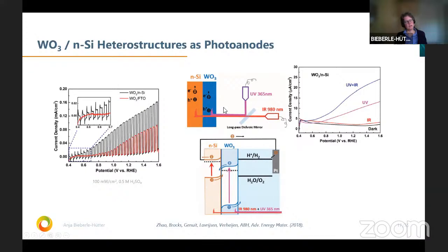And then we did actually a nice study on finding the reason why it is higher. And what we did is we illuminated our samples with either infrared or UV light, or with both together. And this is what you see here. Because the tungsten oxide and the silicon are active with different wavelengths, we could really separate the contribution, what effect is related to the current density in these heterostructures, tungsten oxides.